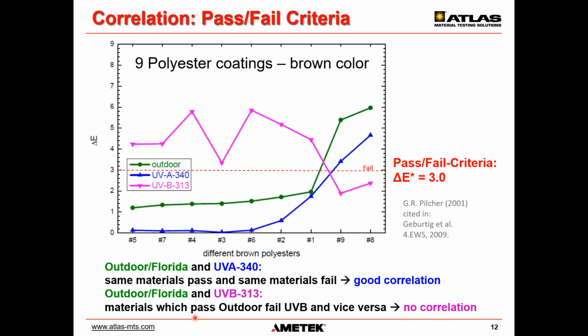If you compare Florida weathering to UVB exposure, remember the last slide, short wavelength exposure is typically very unrealistic. And that's shown by the data here. Actually, it's the reverse order. The materials which pass Florida and pass UVA fail in UVB, and the materials which fail in Florida and fail in UVA pass UVB testing. So a reversed correlation, I would say. But in general, there is no correlation between UVB and outdoor Florida weathering. That's a simple correlation based on pass-fail criteria, where some materials pass and some materials fail.